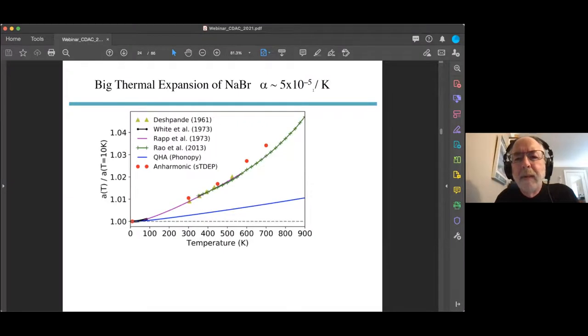So we looked at sodium bromide, where the quasi-harmonic theory, the volume effect, was way off compared to the experimental data. But the ab initio anharmonic theory got it roughly right, except at the highest temperatures. And this is a factor of four. So the referees were very happy that maybe anharmonic theory is needed here, unlike silicon, where they weren't really convinced, quite frankly. But the phonons were very interesting in sodium bromide.